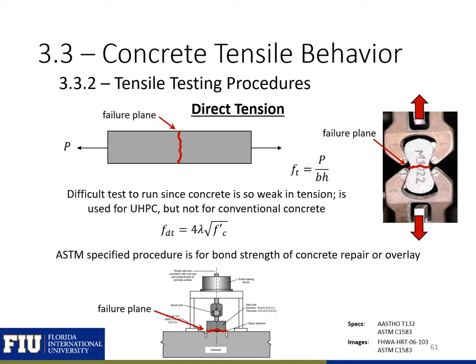This type of test is typically used for two applications. First, it can be used to find the tensile strength of ultra-high performance concrete, or UHPC. UHPC has a very high tensile strength, so there is a larger tolerance with load application. This test is normally run on a dog bone shaped specimen like the one shown on this slide, with the failure plane occurring at the narrow point in the specimen.